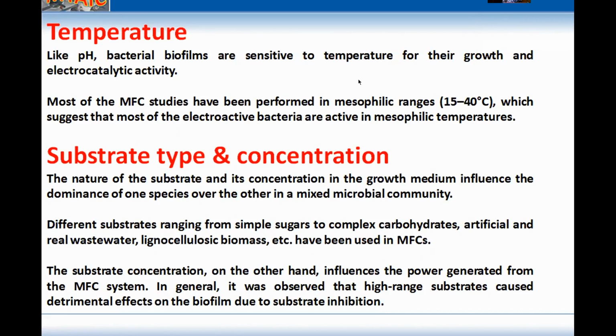Also, temperature greatly affects the bacterial biofilm, as temperature affects their growth and electrocatalytic activity. Most of the microbial fuel cell studies have been performed in the mesophilic range between 15 and 40 Celsius, which supports that most electroactive bacteria used in the microbial fuel cell are mesophilic. Also, the substrate type and concentration have a great effect on microbial fuel cell performance, as we can use different substrates ranging from simple sugars to complex carbohydrates and artificial or real wastewater. Also, it was observed that a high concentration of substrate can have a detrimental effect on the biofilm due to substrate inhibition.